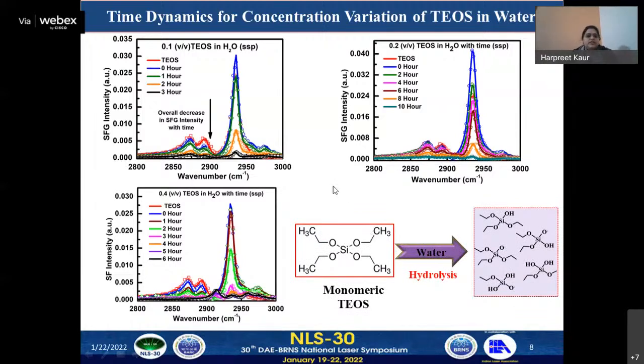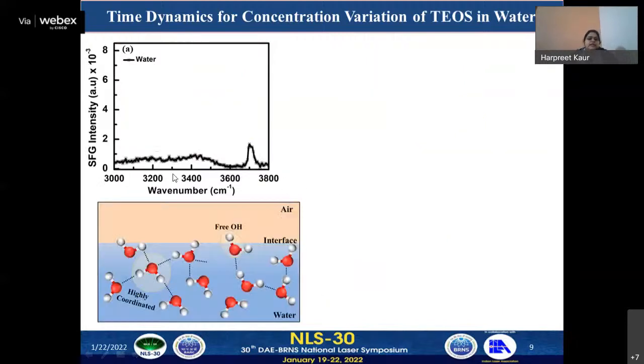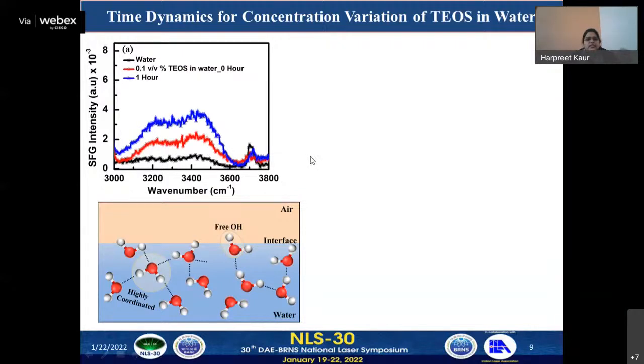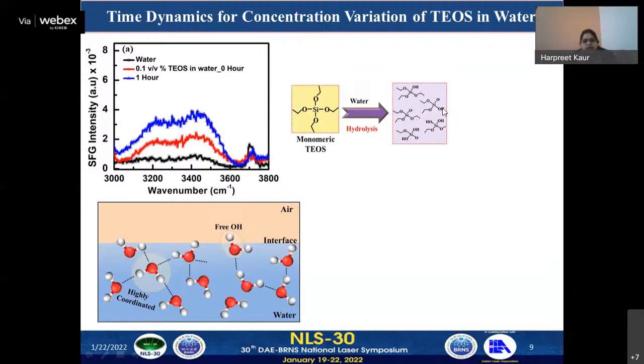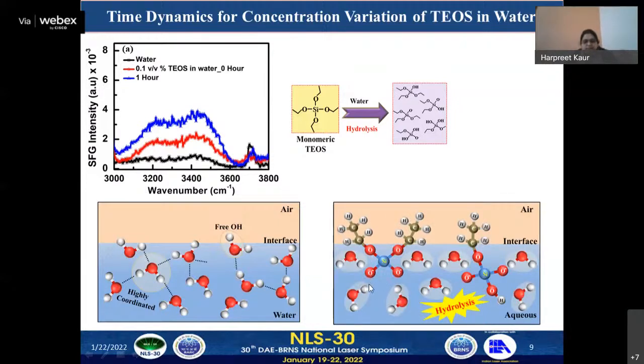And further, in the OH stretching region, we found that there is an overall enhancement in the SFG intensity with time, which confirms that there is hydrolysis at the air-aqueous interface, due to which there is formation of negatively charged moieties, and because of that, there is ordering of the interfacial molecules at the air-aqueous interface.